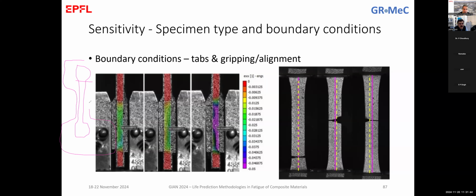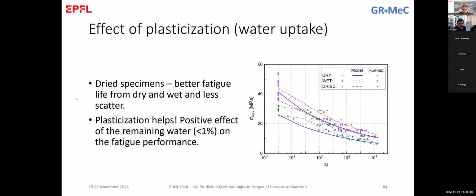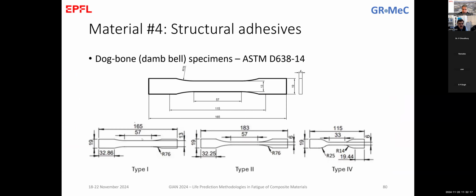So we made a specimen like that with huge areas on the tab. What does it mean? If you press here, you can transfer, because the grip transfers the load in shear. So there you need a lot of area. The more area you have there, the less stress concentrations you have. So the standard might tell you, okay, you have a typical dog bone specimen of this type. But in this case, it might be that this area is not enough. If your specimen is stiff and strong, this area is not enough to transfer the loads. So you need to increase this area artificially yourself, of the specimen itself, to allow the transfer of this shear loading to the specimen correctly and without any specific concentrations.